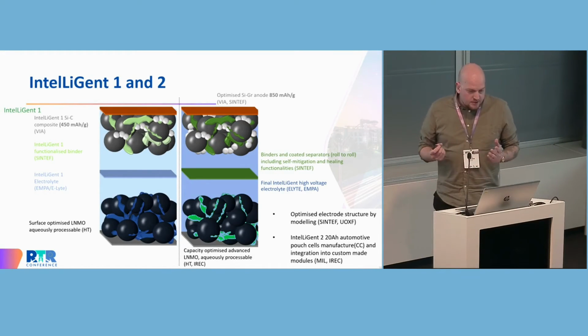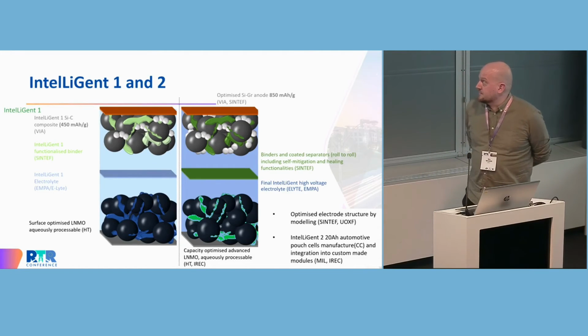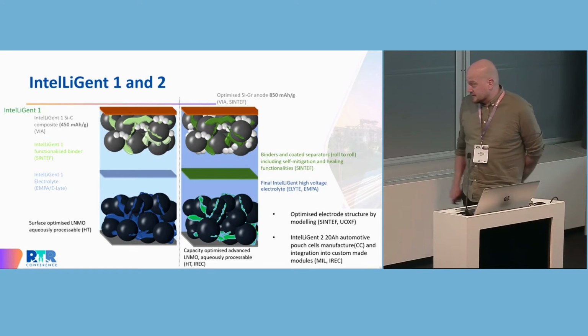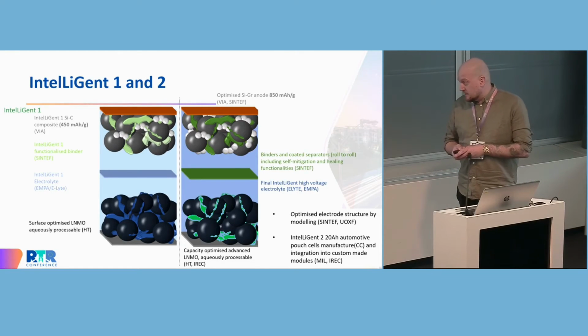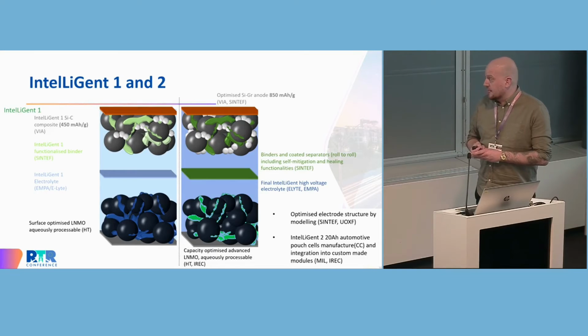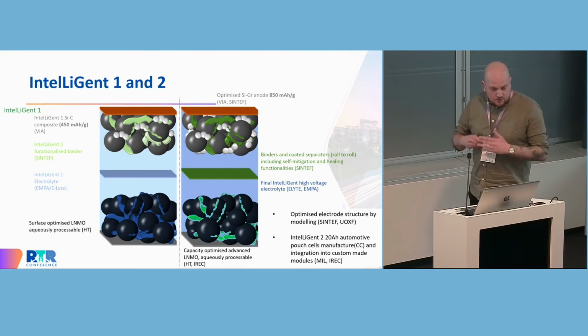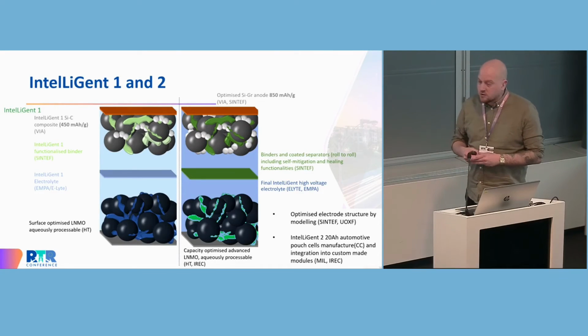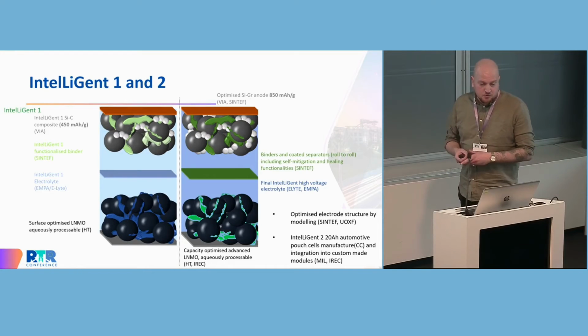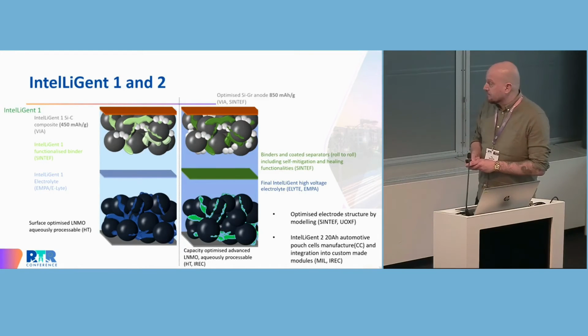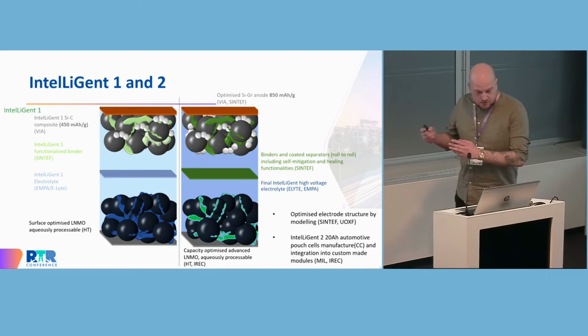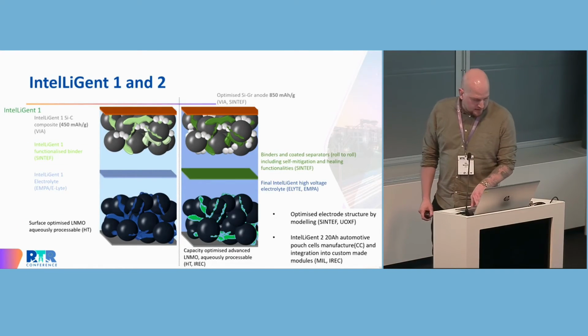The second or final generation then will be the full-fledged Intelligent battery with an anode delivering 850 milliampere hours per gram and capacity optimized advanced LNMO, which is still aqueously processable. Our final Intelligent high voltage electrolyte, and then full-fledged functionalized binders and also coated separators to further trap malign species such as transition metals, but also radicals and Lewis acids. We base this cell design heavily on model-based impacts, and then we want to upscale to 20 ampere-hour pouch cells.